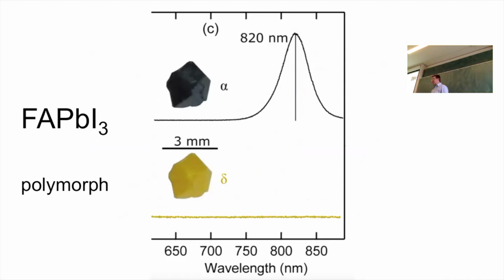And one thing that we can try to do is by using doping. Zinc doping can influence this. And recently also formate doping. So using a few percent of a formic acid type anion can change the phase diagram. One of the most recent papers from Grätzel contains formate anions. So instead of the iodide at the edge, putting formate there, maybe only on the outside, that can influence the stability at room temperature or the phase diagram.